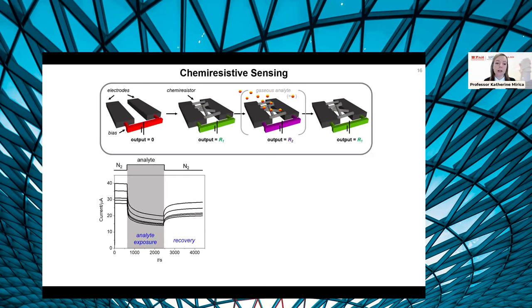So our raw data looks something like this. It's a current versus time plot that changes upon analyte exposure. And as the analyte stream that is being flown over the surface of the device is removed, we can see some recovery. Now, this recovery phase can be informative. What you're seeing on the slide is a partial recovery, often corresponding to partially reversible interactions. But this recovery can be completely reversible or completely dosimetric. And typically, that recovery process can be informative for inferring the kinds of intermolecular interactions or chemistry that may be going on at the surface of the material during the sensing process.